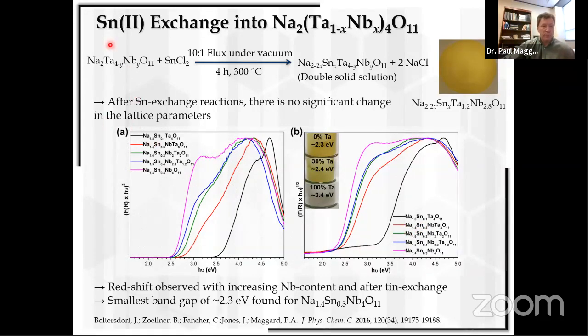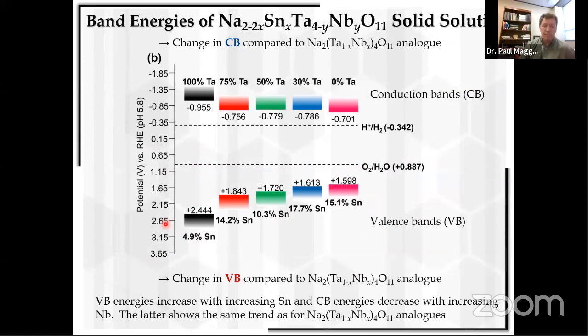And so, for example, we did this in some of the networks, the 2,4,11 phases. We actually did a double solid solution where we mixed tantalum and niobium on one side and sodium and tin on the other using a flux exchange reaction. And we can shift the bands for both the conduction and the valence band to the visible region. For example, here are the valence band positions for different amounts of tin substitution, and here are the conduction band positions for different amounts of tantalum substitution.